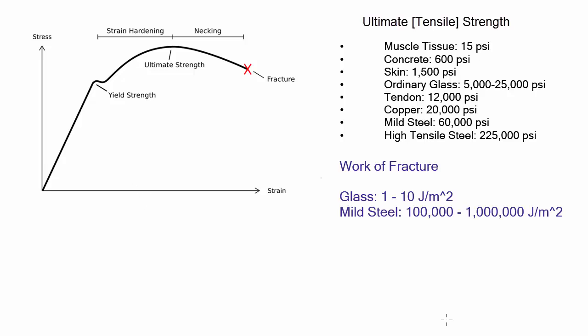Here we see the work of fracture of glass and mild steel. It takes from 1 to 10 joules to fracture all the bonds along 1 square meter of glass. That's not very much, which is why it's rather easy to break glass. Steel, on the other hand, doesn't require energy just a few times greater, but upwards of 1,000,000 times greater. Steel requires 100,000 to 1,000,000 joules per square meter. That's significantly more energy to break a piece of steel, and that's why it's much more difficult to break a piece of steel. Ultimately, breaking comes down to two things: the ultimate strength and the work of fracture.